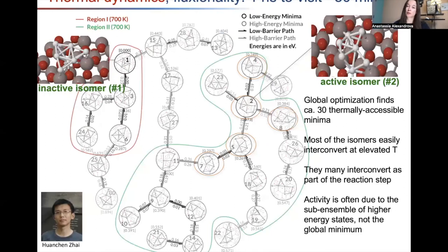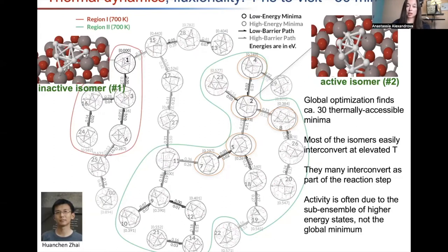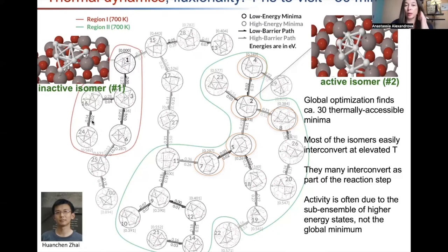This charge is very important for activating ethylene, so this divergence in behavior is suggestive of the differences in catalytic activity these clusters will show. The reality for Pt7 is: before any reagents arrive, we have that many minima that are thermodynamically and kinetically accessible. We computed the full isomerization network for about 30 different isomers, and from the barriers of backward and forward isomerization, we see all of them can be visited in under one nanosecond.